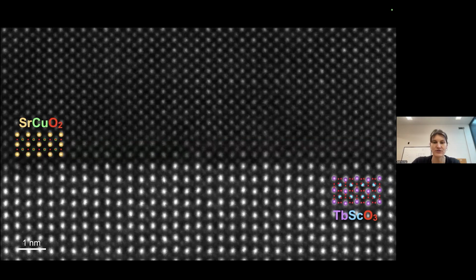And so this, I think, is a kind of image that will be familiar to many people. But this is a good representation of a lot of the types of data that I work with. So this is a high angle annular dark field, or HAADF STEM image. And what you see on the top is this strontium copper oxide material, which has been grown in a very careful method that I'll tell you a little bit more about, on top of this other terbium scandate material. And so again, you can see from the microscopy perspective, we can clearly tell the two materials apart. We can observe a very abrupt interface.